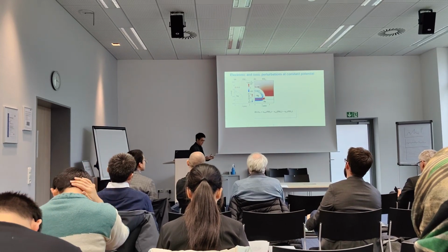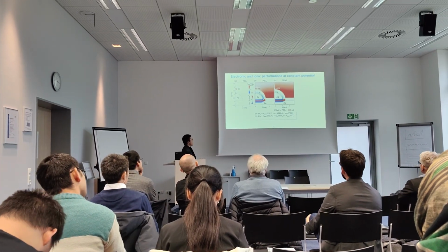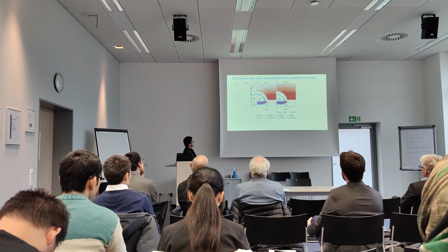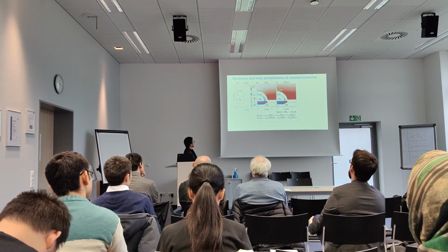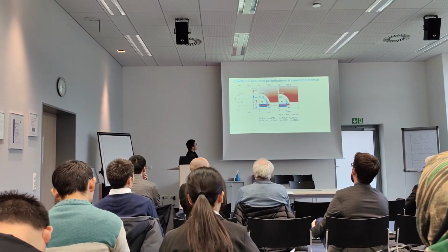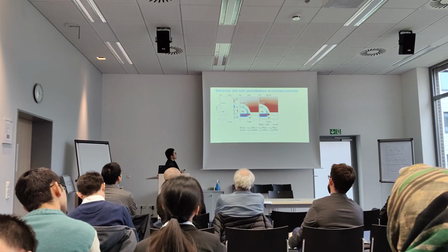So we want to visualize this effect on the potential scale. Now what we do is we reduce the potential by 160 millivolts. What do you get? We recover the local electronic state. So here, it's the same as here. Despite that, the local ionic state deviates further from the previous case. You see? So that means their deviations are in opposite directions.